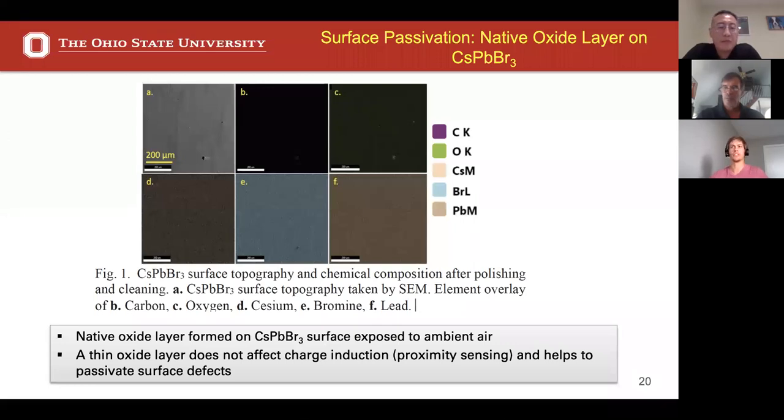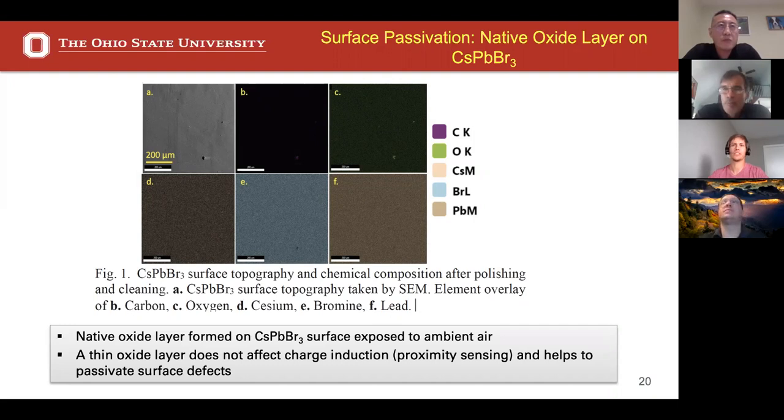So one thing I'll mention is I worked on a project using urea hydrogen peroxide as a gas phase passivation to accelerate the oxidation that you see at the surface. And we could increase the steady state PL signal by an order of magnitude with that for perovskite thin films. So it might be something that you want to try if the surface oxide has a big effect.